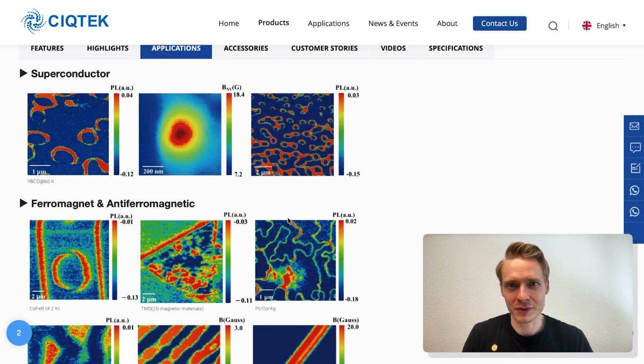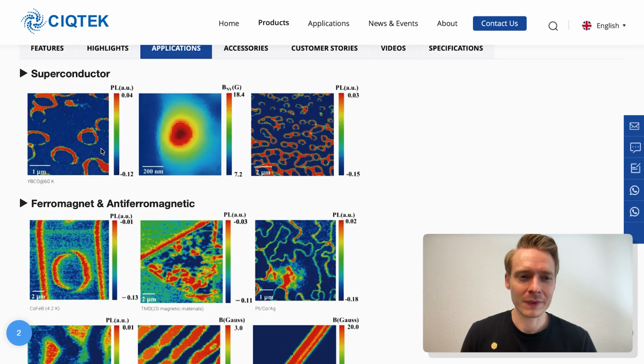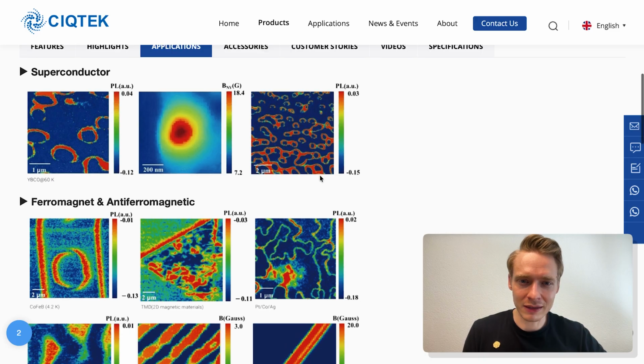Here you see a couple of images from the applications. We talked about superconductors before, right? So there's a so-called type 1 and type 2 superconductor. In type 2 superconductors, usually these are the stronger ones, so the higher critical temperatures, they can absorb so-called flux quanta. So you see these magnetic fluxes that are penetrating the superconductor in specific areas. And these can also move in the surface, and they also reconfigure every time you warm up and cool down the system. And with these microscopes now you can actually measure them very nicely on the surface.